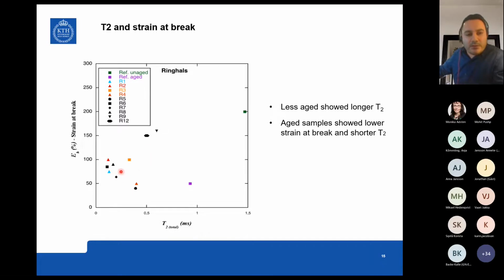So just to point out, this is the cable insulation material that we've managed to measure. So what we've done is that we've known the cable dimension, and by tuning the RF frequencies, we are able to measure at a certain point inside the cable. So we measured essentially the cable insulation. And this was a quite tiresome job also that we had for the mechanical testing. So we had to cut out these pieces of cable insulation and do some strain at break testing just to get a feeling of where in relation they are.